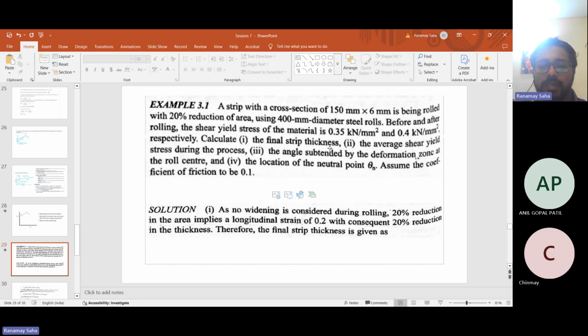You have to calculate the final strip thickness, the average yield stress during the process, the angle subtended by the deformation zone at the roll center, and the location of the neutral point N. You can assume the friction coefficient to be 0.1, right? One tip is that since in the rolling process, widening or spread is considered to be zero, the 20% reduction implies a longitudinal strain of 0.2, with consequently 20% reduction in the thickness, right? So therefore, the final strip thickness will be 80% of the initial thickness, okay? 80% of 6 mm. So please try to attempt, and then we'll see the solution.